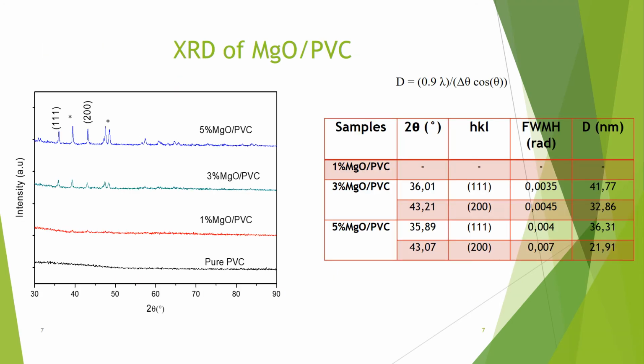We move now to the characterization of the polymer nanocomposite. We start with XRD diffraction of magnesium oxide PVC. From the X-ray diffraction spectra, the pure PVC film shows an amorphous structure. However, with the addition of magnesium oxide nanoparticles at 3% and 5% in the PVC matrix, we obtain a crystalline structure with appearance of two peaks at 36 degrees and 43 degrees corresponding to the cubic phase of magnesium oxide.